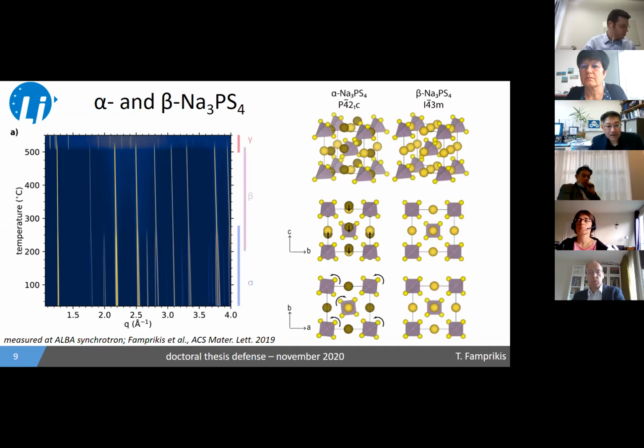The difference between the two essentially is that in the tetragonal model, the sodium positions need to be described by 2 crystallographic sites, distinct ones. And then in order for the transition to happen, this second sodium site just needs to shift along the C-axis. And simultaneously, a small rotation of the PS4 anion needs to happen also about the C-axis to get the perfect cubic symmetry.